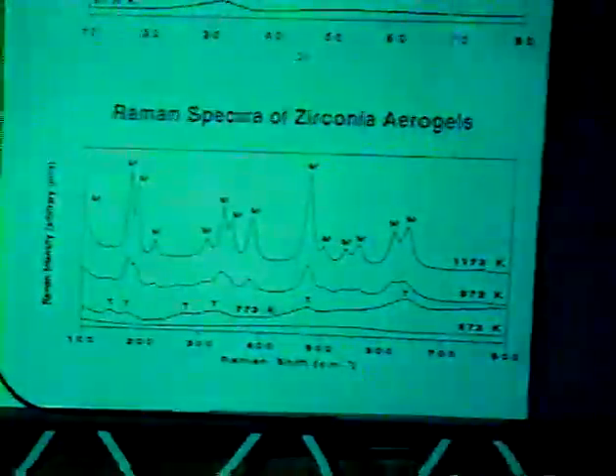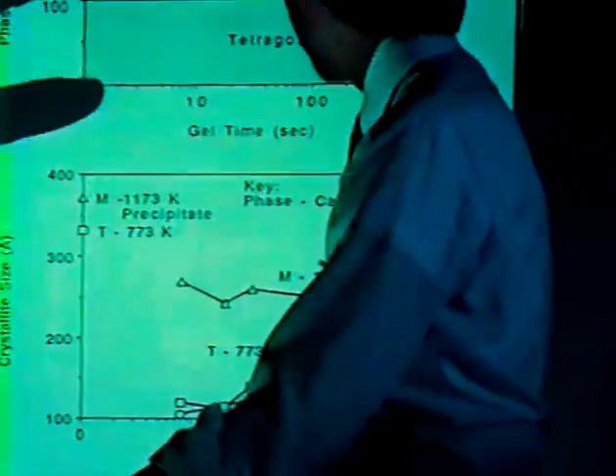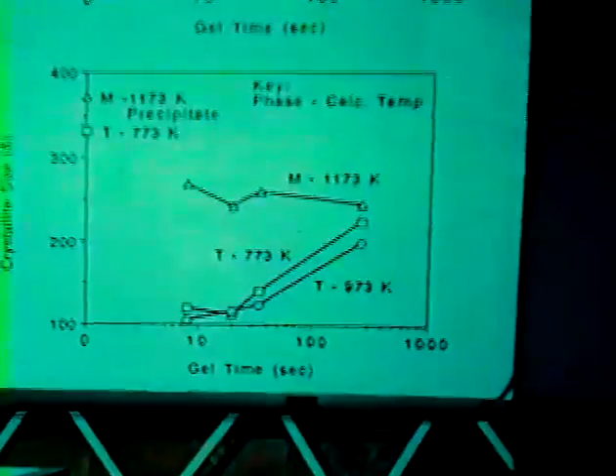Now, in order to confirm the structural assignments, we looked at the same series of samples using Raman spectroscopy, shown at the bottom panel, and the structural assignments agree. Again, at low temperature, the material is X-ray amorphous. It first crystallizes into the tetragonal form of zirconia, and then upon further heat treatment into the monoclinic form. Now, the fact that we can stabilize the tetragonal zirconia first before the transformation to monoclinic is in itself not a new finding. In fact, many other investigators have reported the stabilization of tetragonal zirconia at room temperature. On the other hand, the literature is still divided as to what is the cause of that stabilization.